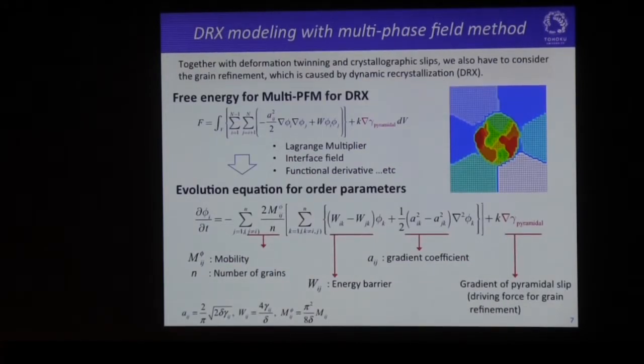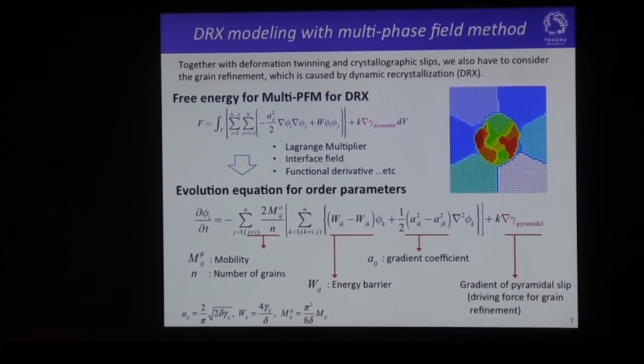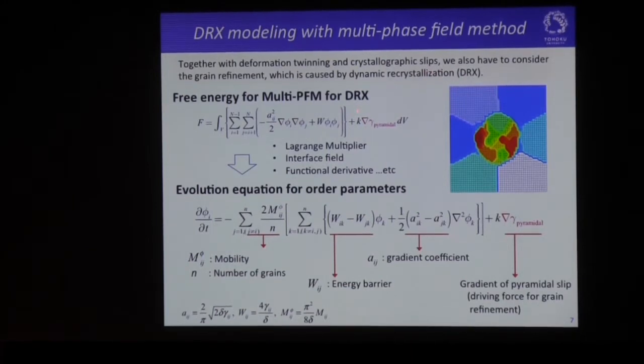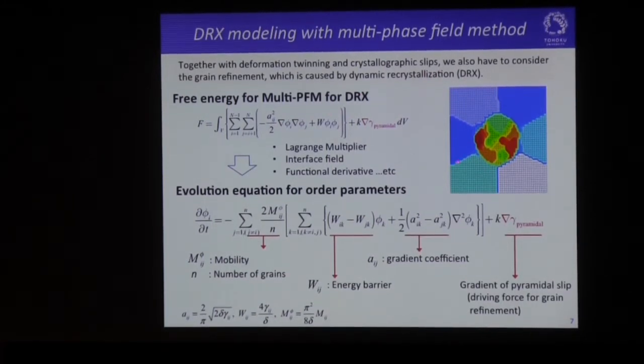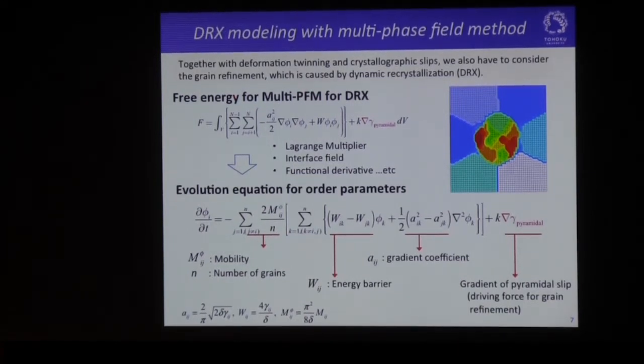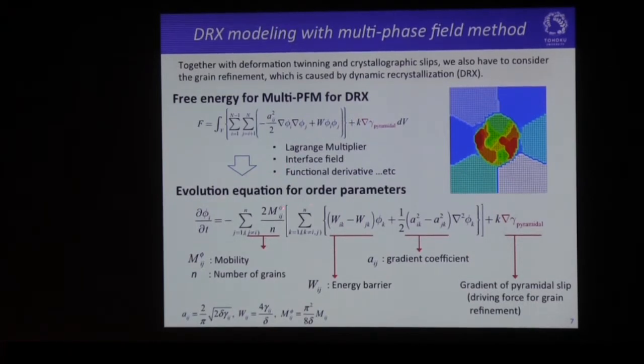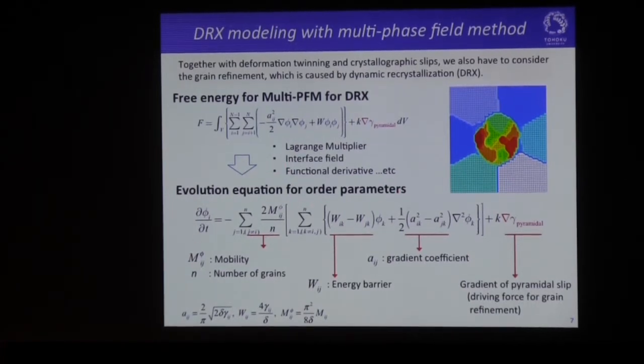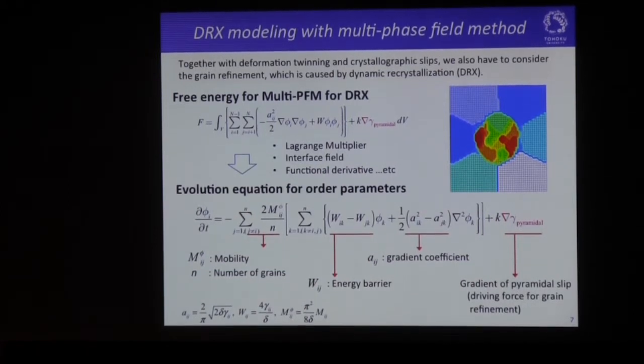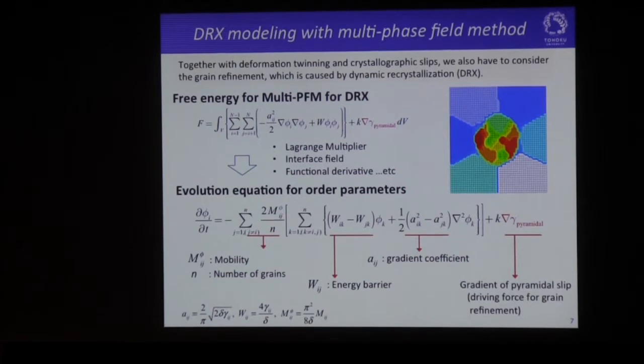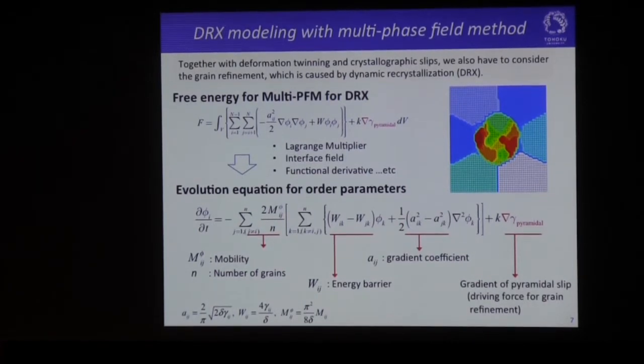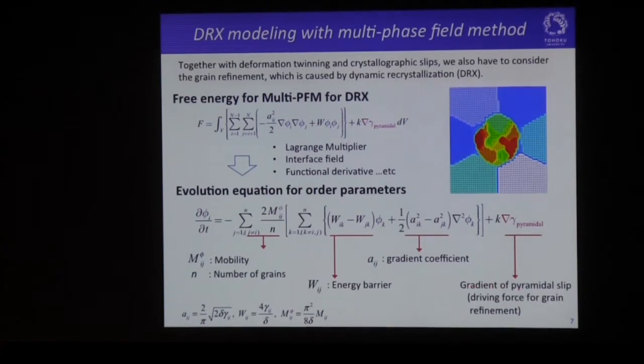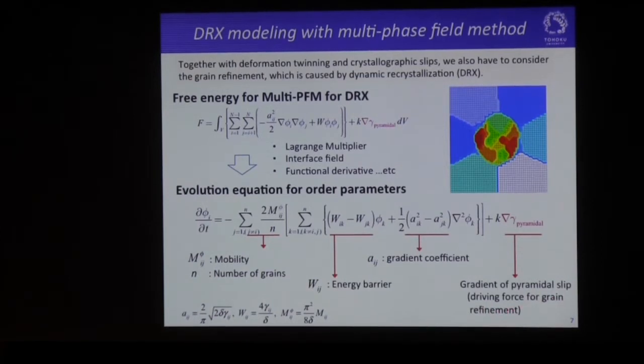Together with the deformation twinning and the crystallographic slips, we also have to consider the grain refinement, which is caused by the dynamic recrystallization. So, in order to represent this kind of grain refinement, we employ the multi-phase field method with this free energy. And then we take the standard process to derive the evolution equation for order parameters. This is the evolution equation, which involves some standard terms here for the multi-phase field method. But here you can see the special term composed of the gradient of pyramidal slip that we assumed as a driving force of grain refinement. Okay.